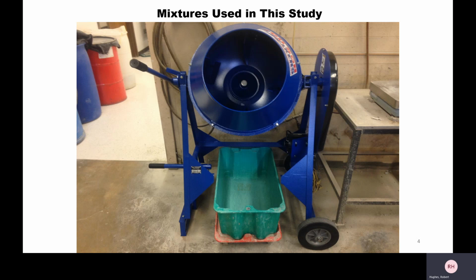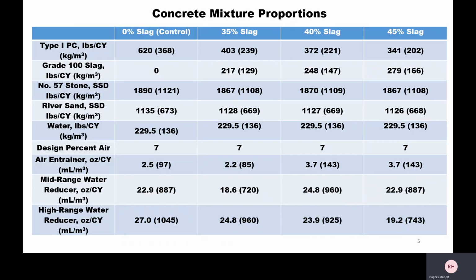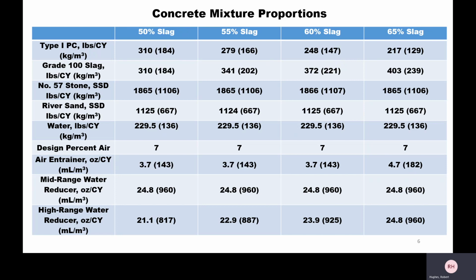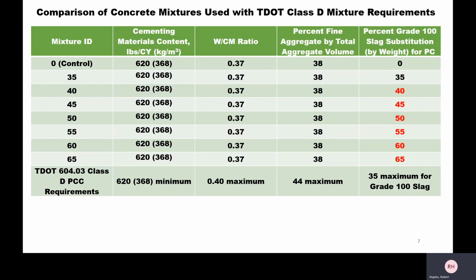So first, let's look at the different mixes that we used for this. Our control is a 0% slag, so 620 pounds per cubic yard, which is the TDOT minimum. And you'll see all the TDOT requirements in two slides. But you'll notice that each of these cells will add up to 620 because of the substitution factor. And this is our 35, 40, and 45% substitution, 50, 55, 60, and 65. So eight mixes altogether.